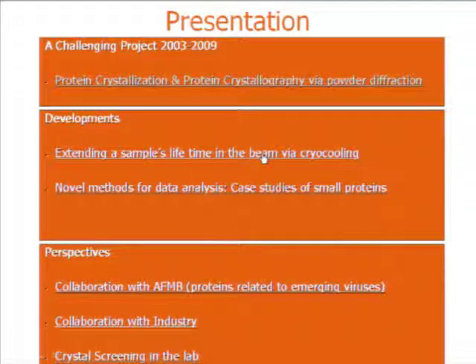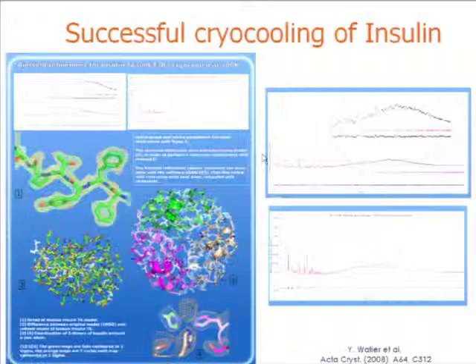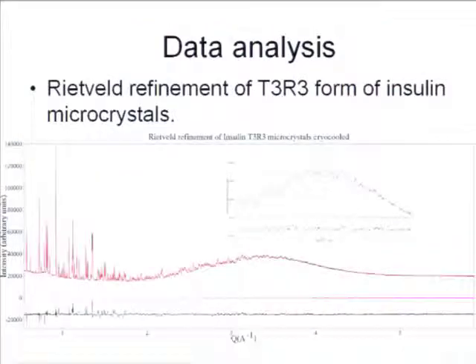So John mentioned the cryocooling process, which is not simple because you have to be fast and find the right cryoprotectant to avoid freezing of the water, which occupies 50% of the unit cell usually. This is a successful case where Yves Watier, by using Kapton tubes and various other tricks, managed to cryocool two polymorphs of insulin, which are called T6 and T3R3. Both correspond to hexagonal insulin, and by cryocooling, we extended the sample's lifetime by a factor of 100. So data could be collected in this region.